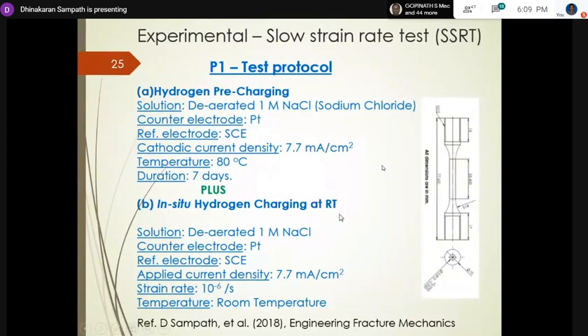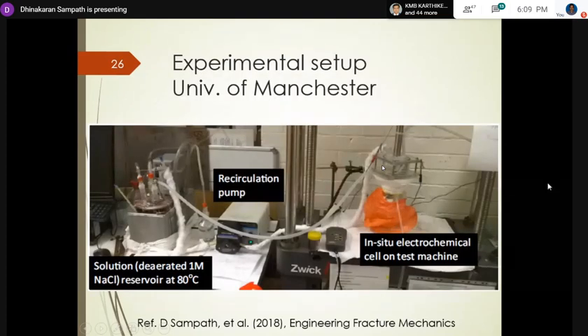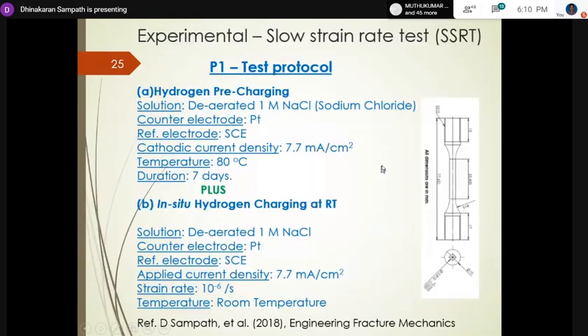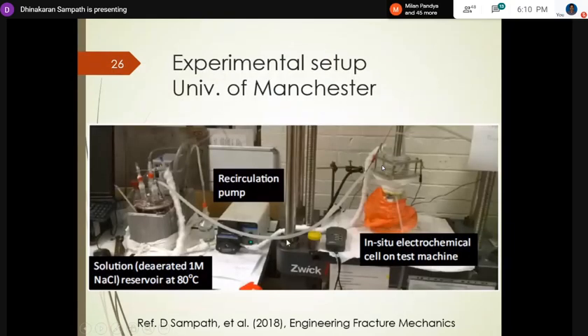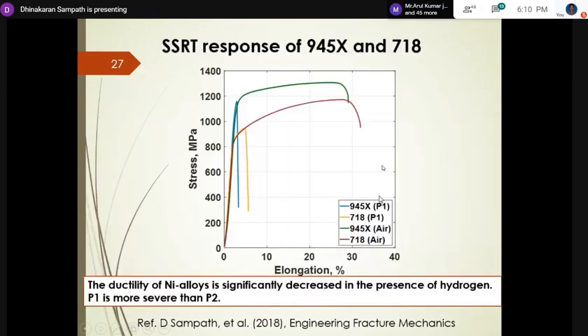And then we did the in situ hydrogen charging and then conducted the tensile test. That means while conducting the slow strain rate tensile test, we simultaneously charge the sample with hydrogen. This is the experimental setup. We have this pull rod and mount the electrochemical chamber around the subsize slow strain rate tensile specimen, and we have a recirculation pump to provide deaerated sodium chloride solution. Here we have a three electrode system to effect hydrogen generation.